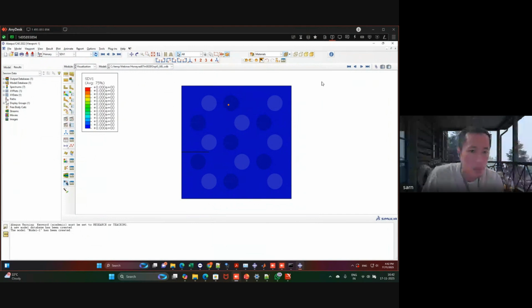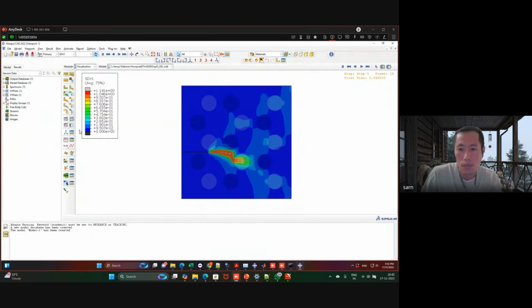Now I will run this. You can see that, as I said, this region is the harder material and this is the softer material. The softer material attracts the crack, so the crack tries to move towards the softer material. And here we have a harder material, and it tries to avoid this harder material. Why is it happening like this? Because of the local stress distribution.